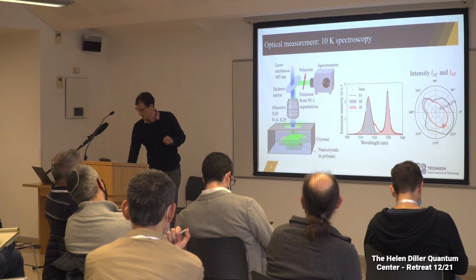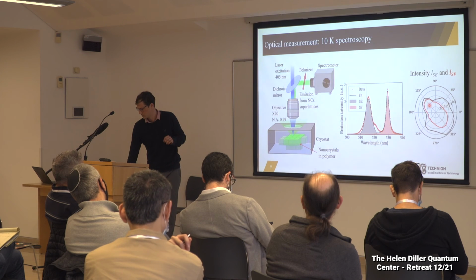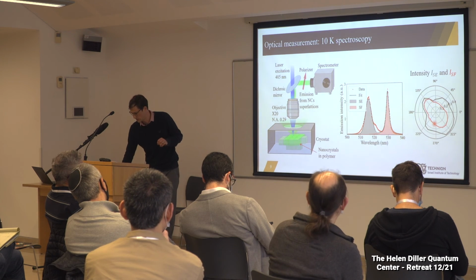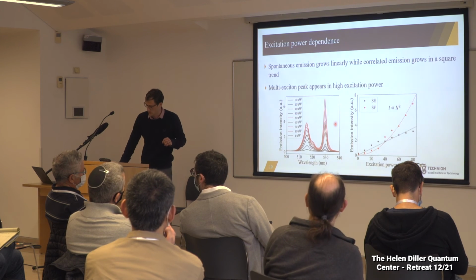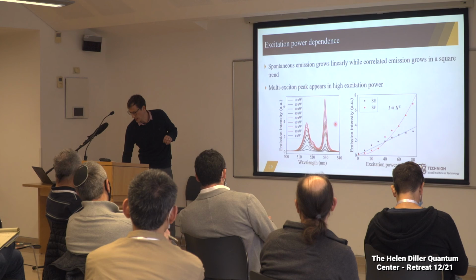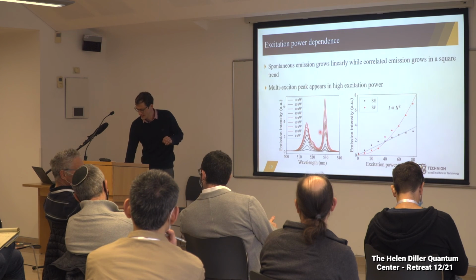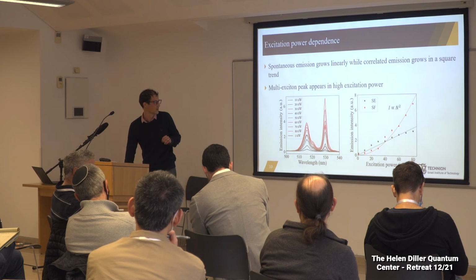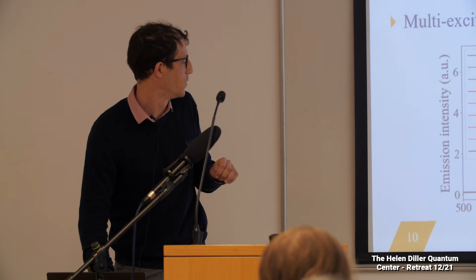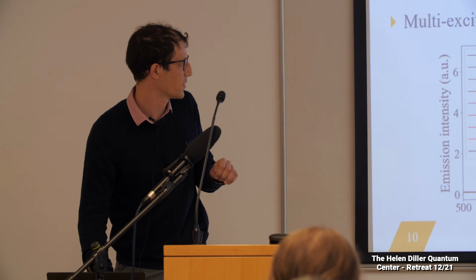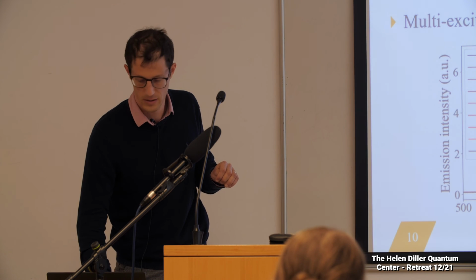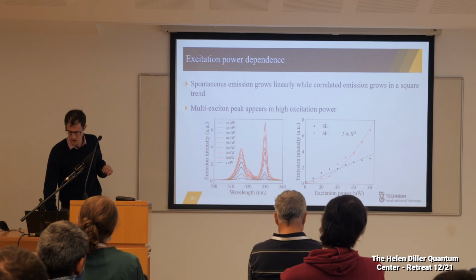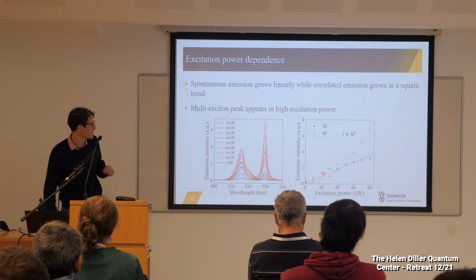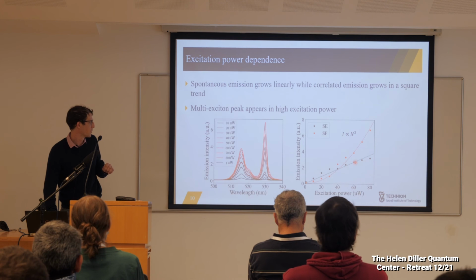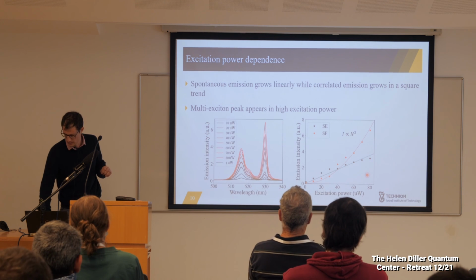We see that the superfluorescence emission is polarized, unlike the spontaneous emission, which is pretty much what we expect. Another nice thing is that once we increase the intensity of the excitation, we see that the superfluorescent peak grows faster than the spontaneous emission peak. It follows a quadratic trend, where the spontaneous emission follows a linear trend. We also see growth of the multi-exciton peak, which takes some of the energy from the spontaneous emission, and this is probably what makes it less linear at high powers.